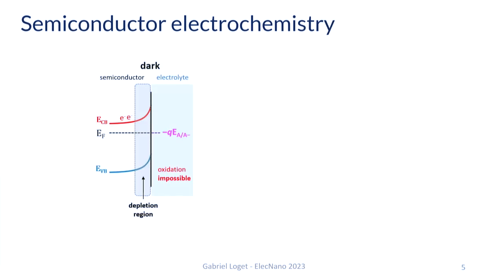When we do semiconductor electrochemistry, of course, we use a semiconductor working electrode, immersed into a liquid electrolyte which contains 1 or several redox species, in this case a redox couple A-. Most of the time we work in conditions where our electrode is in depletion, which means we have the formation of a depletion region here, and we have a band bending. Because of this condition, the charge transfer at the interface is not possible. You see here that the electrons from this species cannot go into the conduction band. So in the dark, the oxidation is not possible in this case.